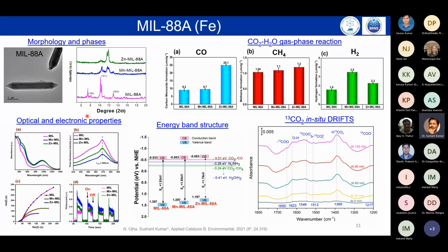First we did the optical and electronic properties. We have seen that the manganese and zinc were performing very close to each other, with the MIL being pretty low in absorbance and also in performance on the electronic and optical properties. Manganese and zinc were neck and neck on the photocurrent, the electron mobility, and also the energy band structure. It was too close to call and to give a clear picture between manganese and zinc, though zinc has a bit of an upper hand, but it was not that far.